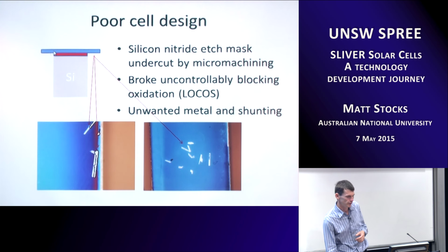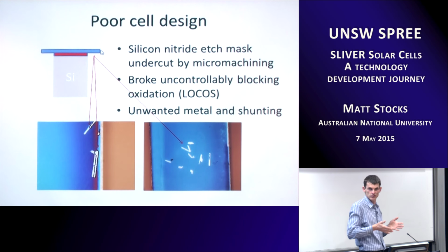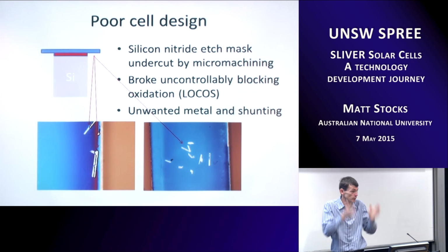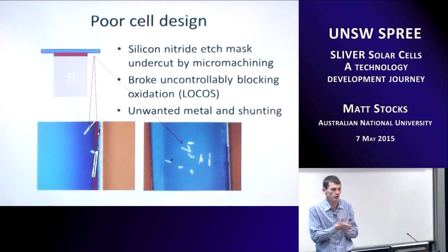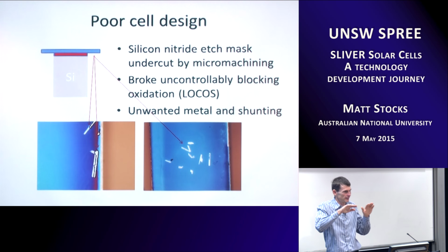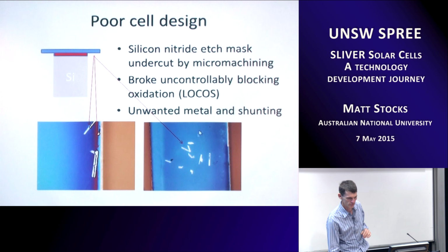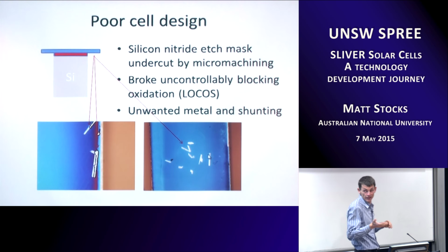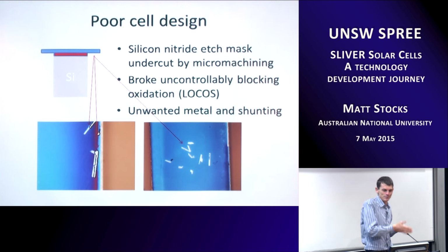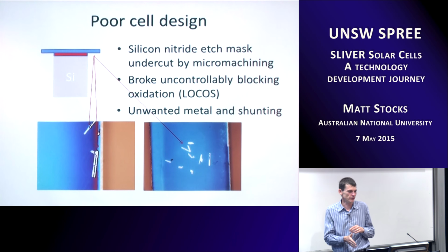So we had this silicon nitride layer, which was on the top of our wafers. We were etching down between these grooves, and there was a bit of undercutting. It wasn't much, only 5 microns, 10 microns of undercutting, because we wanted these really deep, narrow grooves through our wafer. But we had then this uncontrolled breakage. These would come off and they'd land wherever they liked. Sometimes they would land nicely in the middle of the wafer and it didn't actually hurt anything. It didn't cause a problem. But some other times they interfered with the process.